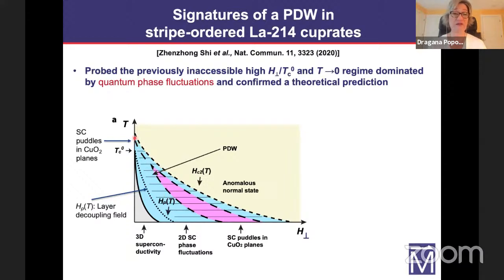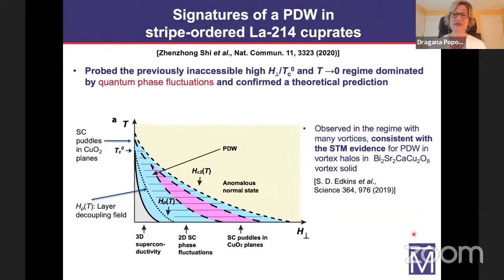Basically, the effect of parallel field is seen all the way up to temperatures where the peak in the magnetoresistance in transport vanishes. So again, we see the evidence for pair density wave when planes are decoupled, when we have a fluctuating superconductivity in the planes. In other words, when we have many vortices. So from that point of view, this is consistent with the STM evidence for a pair density wave in vortex halos in Bi2212.